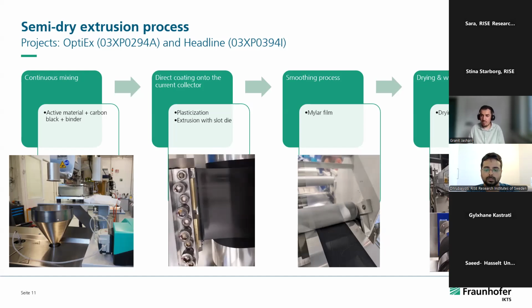So on this smoothing process from the slot die, when the material is going to the current collector, and then between two rollers to do the smoothing, you need in the upper roller to have a film which protects the active material to not be sticky on the roller of the calendaring. And that's why we use a mylar film.